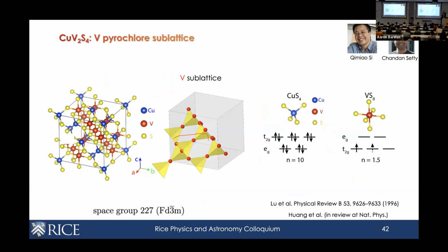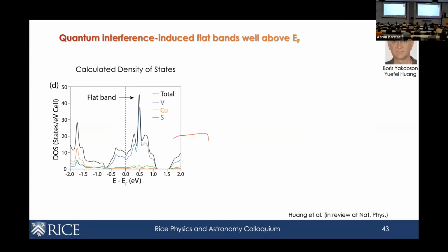To make a long story short, we can consider this material as dominated by the vanadium sublattice, which is a pyrochlore sublattice. If you look at the calculation of density of states, which was carried out by Boris Yakobson next door, you can see that indeed the density of states is dominated by vanadium near the Fermi level, which means the pyrochlore lattice actually dominates the physics in this material.